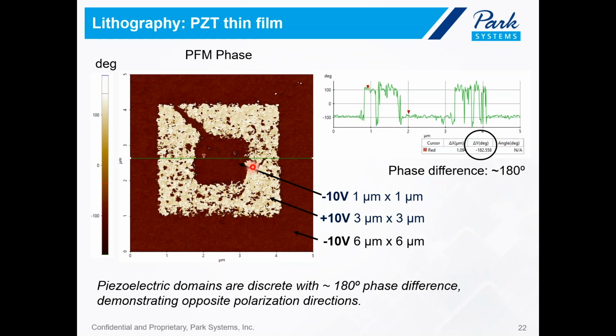DC bias. So in this case, we would expect that the inside square right here, the 1 micron by 1 micron area, and the outside square right here, the 6 micron by 6 micron area, to have the same polarization direction, as they were both scanned with negative 10 volt DC bias applied to the tip. So to check that, we drew a line profile along the phase image. The line is right here, and the line profile is shown here.